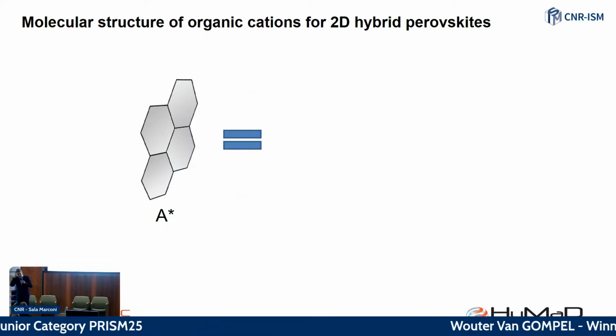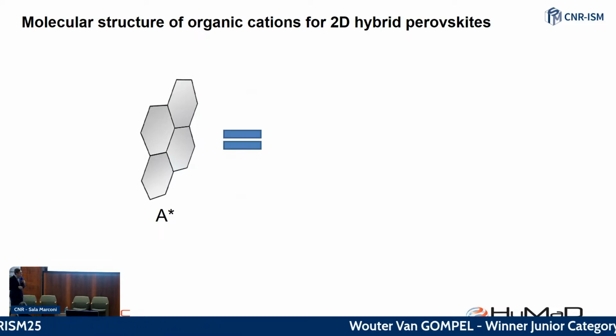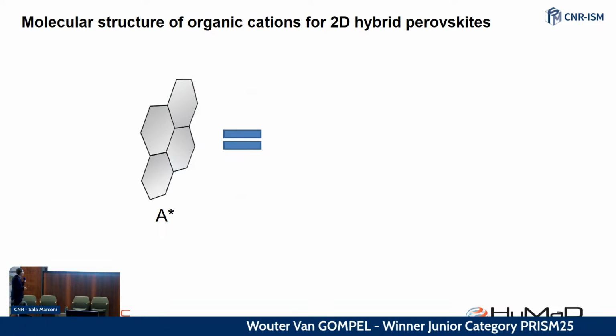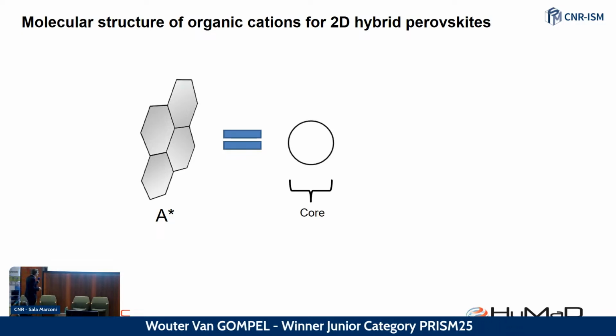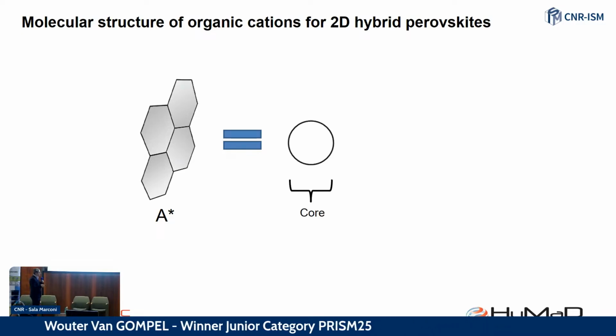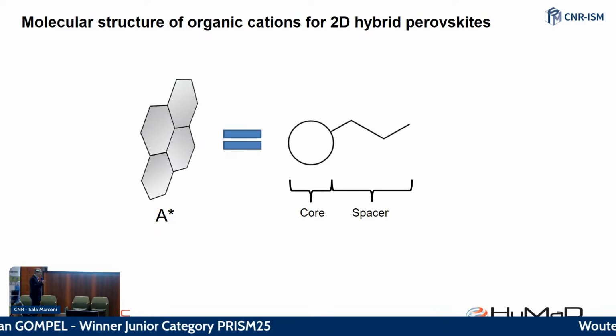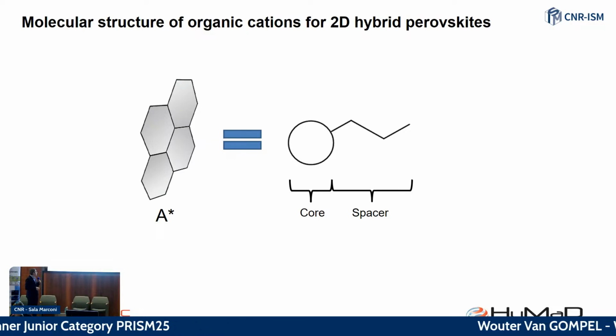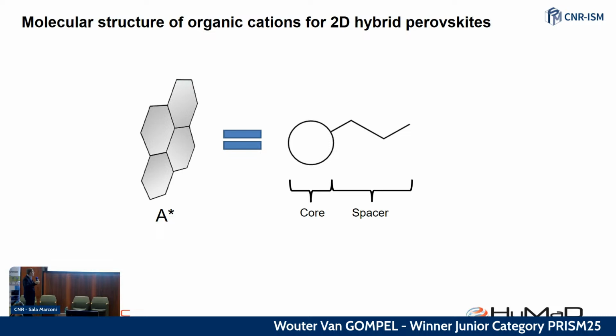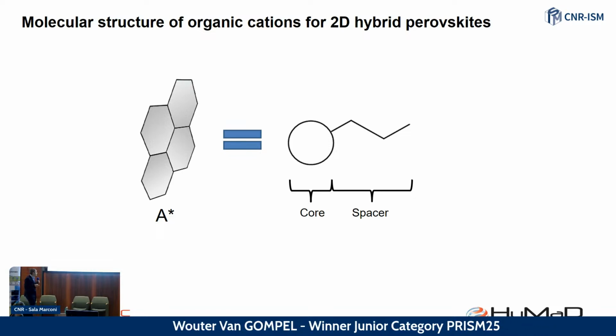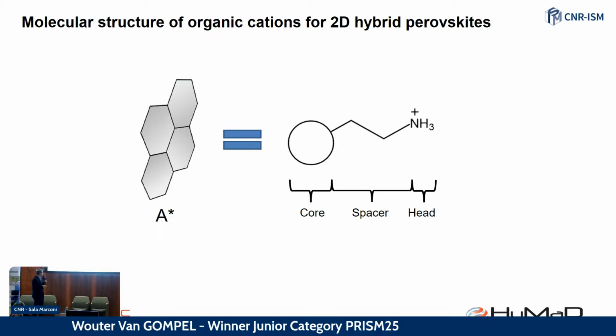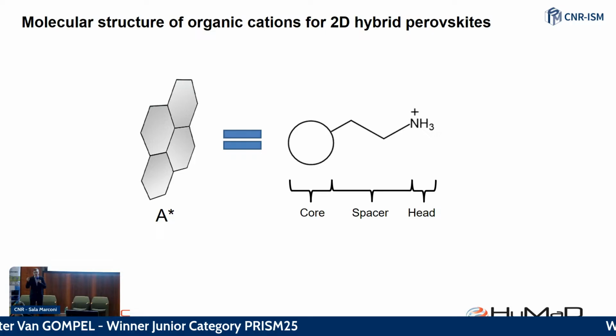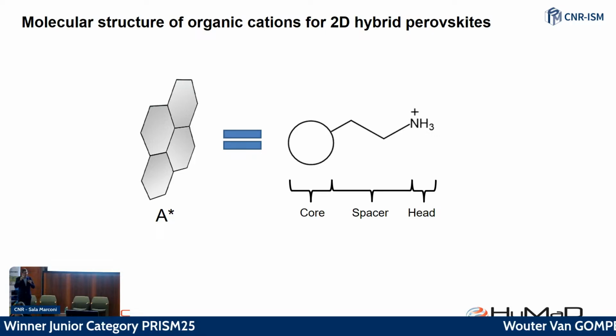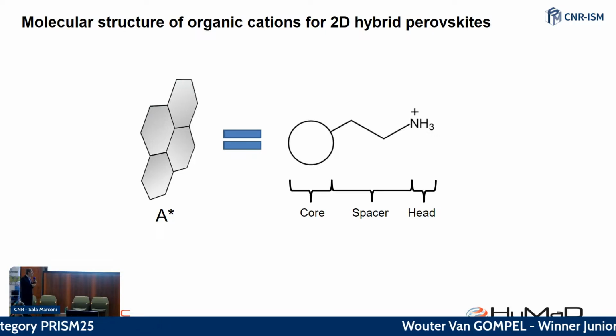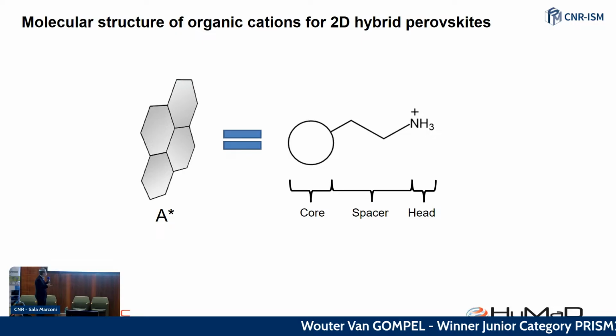So, okay, for now it's still quite schematic. So what is this organic cation in general? You have an organic core, which can be quite varied. You have a spacer, an alkyl spacer, which you need because of steric effects. You cannot put the bulky organic too close to the inorganic layer. And then you have an ammonium head group. And this ammonium head group is essential to tether the molecule to the inorganic framework via hydrogen bonding and via Coulombic interactions.